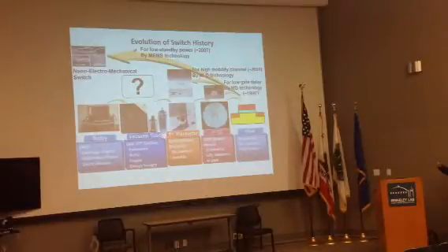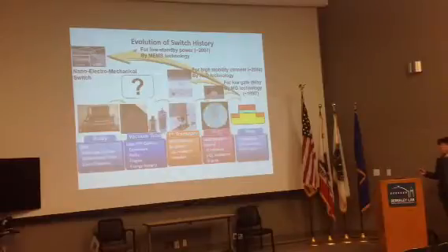But as devices advanced and scaled more aggressively, we now consider using metal as a gate again, and we recently started to replace the silicon channel with a germanium channel, since germanium itself has better carrier mobility characteristics, and goes beyond.